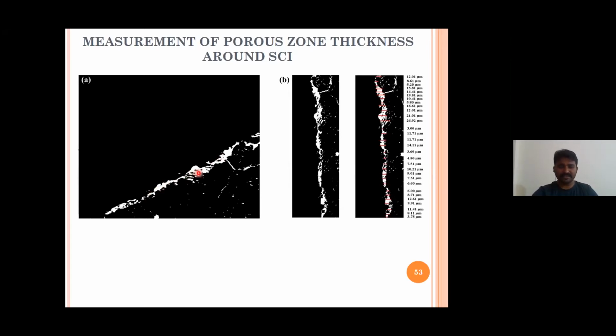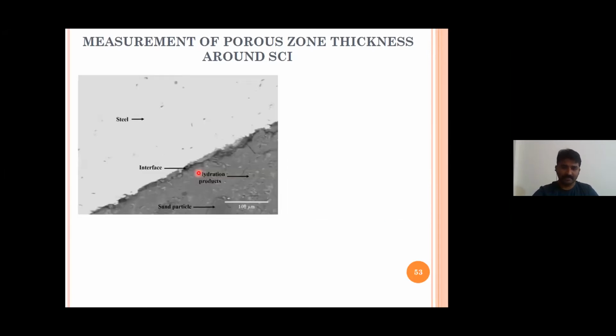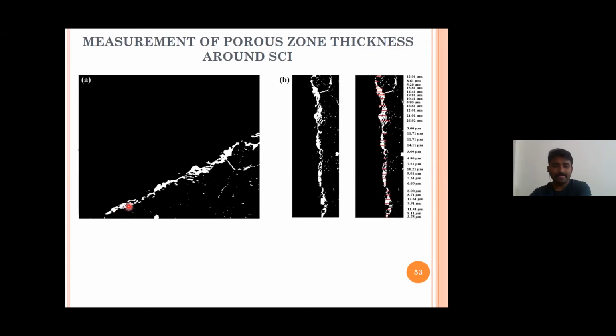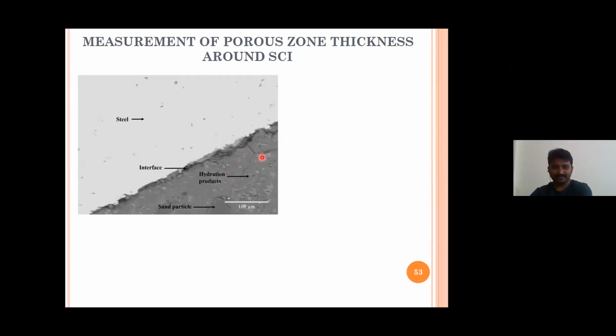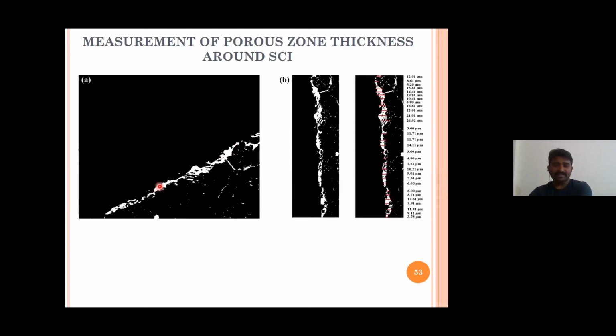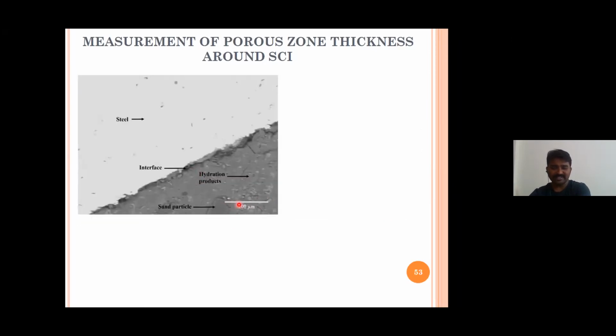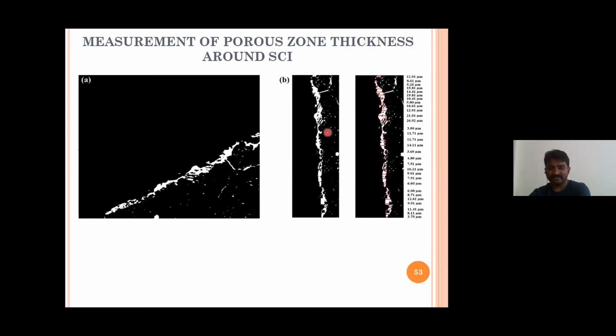See the variation? Here, as you can see, if I threshold this SEM image with a gray value of 42, you're observing this. The other parts are made black, so I'm concentrating on this particular part. See here, there was a crack. You can observe that crack here also. Can you make out that difference? So that is the porous zone which I'm interested in. I have to measure the thickness of this porous zone. If this length is 100 micrometers, then I'm interested in identifying how much this distance, that thickness, is. That thickness comes out to be these values. This analysis we have done in the image analysis tool called ImageJ.